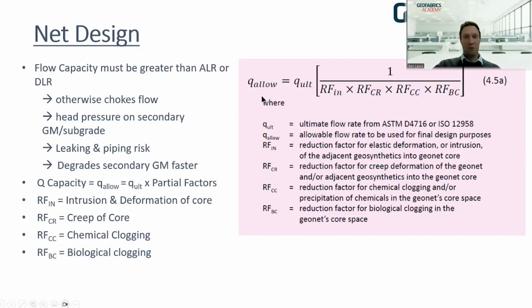So we can work out what the Q allowable will be. We can work out the ultimate flow capacity of a net through transmissivity testing in the laboratory, and then we can apply some reduction factors to account for site conditions. Those site conditions might be intrusion, deformation of the core, that could be from geotextile basically pushing in, creep of the core, chemical clogging, and biological clogging. So there's a number of factors there.